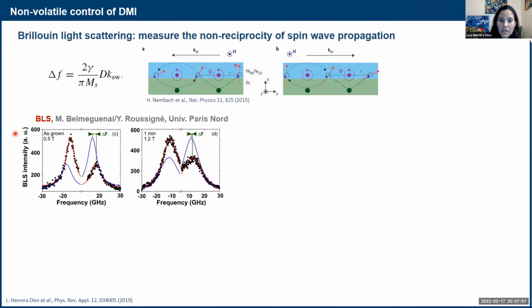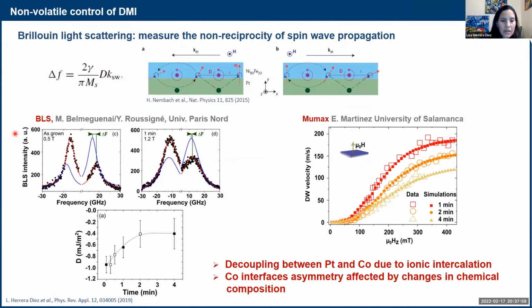And if we compute this delta frequency, then we could end up with a value of the DMI. So that's how we obtain DMI. And here we could see that as a function of the time that we apply the electric field, so here the voltage is fixed, and we just leave the sample longer and longer in the electric field. So that means that we get more and more oxygen inside, basically. We see that the absolute value of the DMI is decreasing.